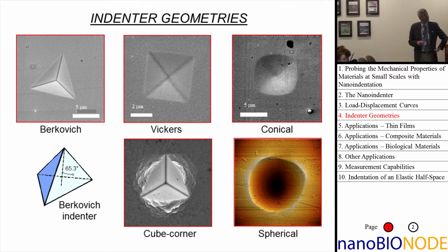The reason we like that one is that a 3-sided pyramid naturally terminates at a point, and so you can maintain geometric self-similarity to very small depths. That is very different from what happens with the Vickers indenter, which is this classic thing used in microhardness testing. That's a 4-sided pyramid, and unless you're very lucky, a Vickers pyramid does not terminate at a point, it terminates at a chisel edge. It's like the roof line on a house.